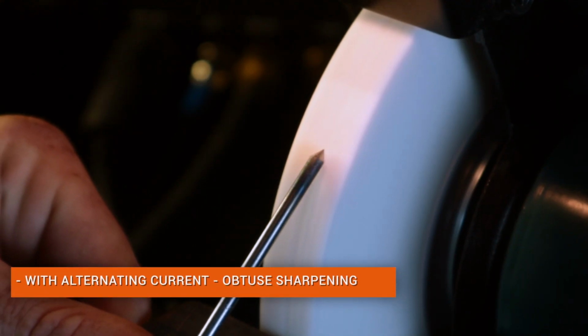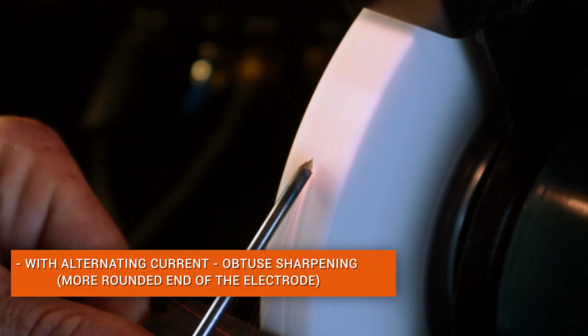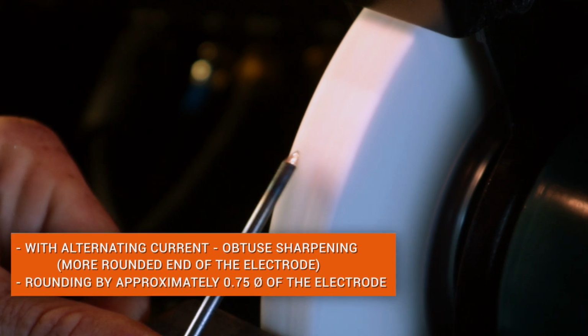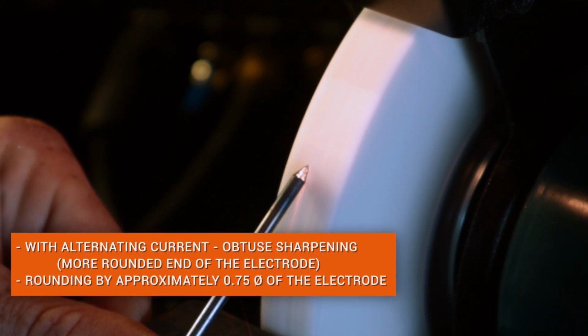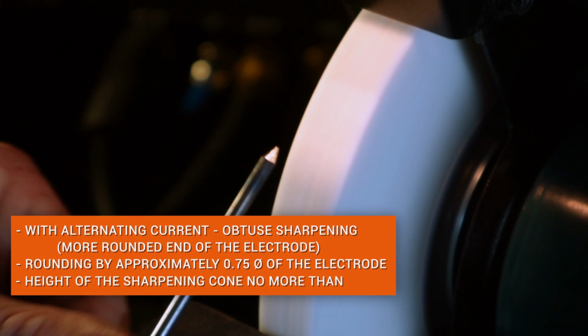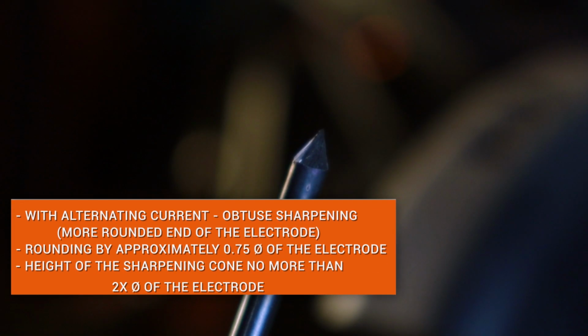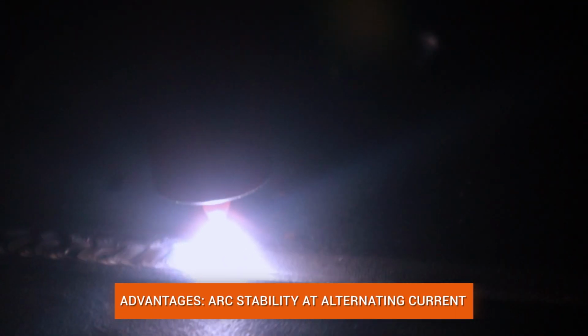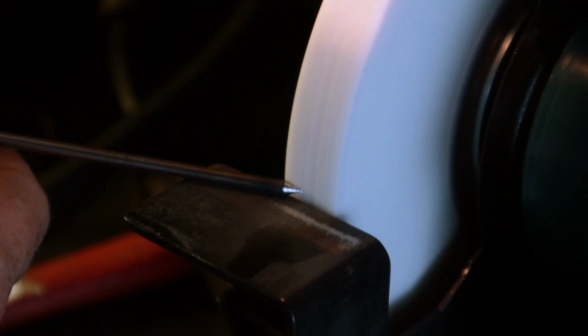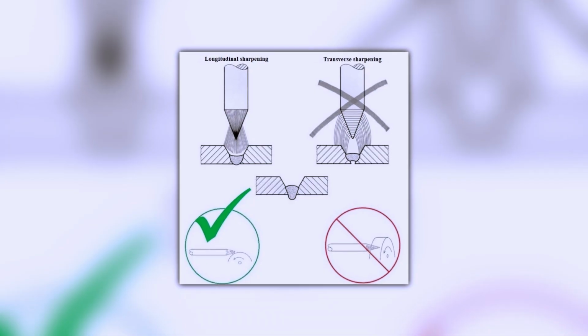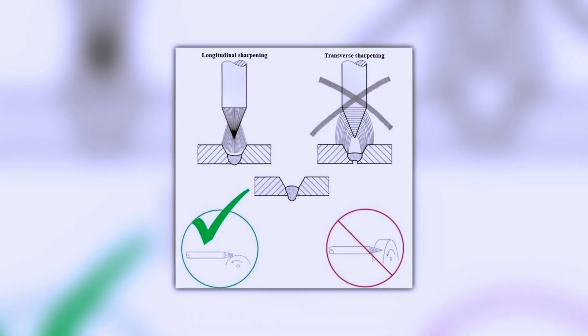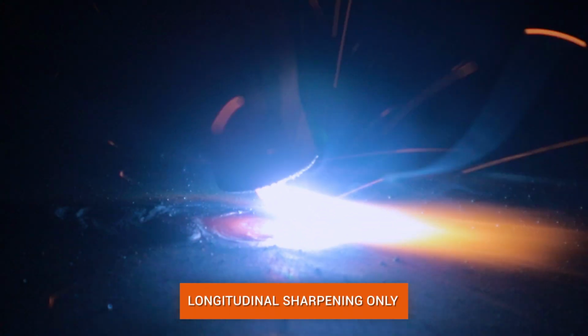When welding with alternating current, the tip of the electrode should be slightly rounded by about 0.75 of the electrode diameter, and the height of the sharpening cone should be no more than 2 electrode diameters. This is due to the use of alternating current in welding. Rounding helps to increase the stability of arc burning. It is also necessary to remember the direction of sharpening the electrode. The sharpening marks should be along the electrode, since with transverse sharpening the arc will be defocused, which will greatly complicate welding.